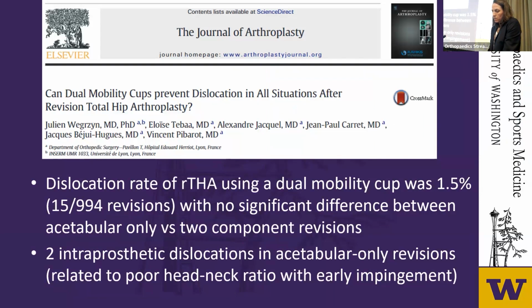This was a continuous series of about 1,000 revision total hips in which dual mobility was used for all these revisions. They had a 7.3 year mean follow-up, and the dislocation rate was only 1.5%. The intraprosthetic dislocation rate was 0.2%. So dislocation rate was considerably lower than in some of the other studies that I previously cited.